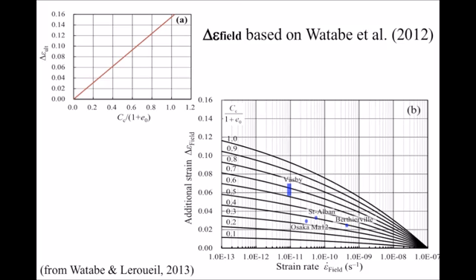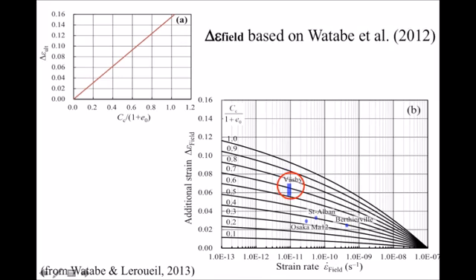If you want a more accurate value and a more practical one, here is delta epsilon field versus the strain rate in the field. And for example, for Väsby, the viscous strain to add to the settlement calculated on the basis of the 24 hours odometer curve will be of about 6%. Now